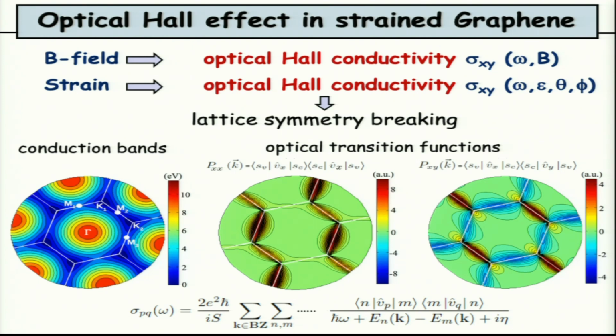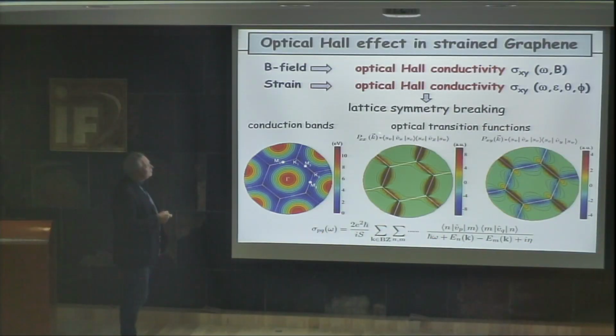So when we calculate the optical conductivity in the system using the Kubo formula, we see that for the optical conductivity, we always have positive value for the optical transition function. So that's why sigma xx is always positive. Okay? Of course, you have different peaks due to the presence of different maxima in the Brillouin zone on the different values of M in the system. On the other hand, if you calculate the optical Hall conductivity, so sigma xy, and you look at the optical transition function corresponding to this Hall conductivity, you see that you can have both positive values and negative values in the system depending on the M point. So for example, for M1 it's negative, for M2 it's positive, and M3 again it's negative.